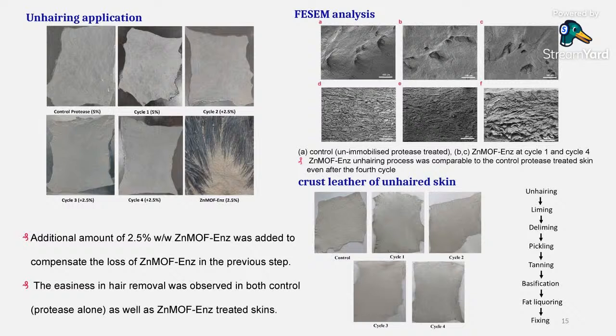Then we checked whether, after adding the ZnMOF in each cycle, the ZnMOF is doing any damage to the follicles, and whether the surface is smooth or not. For that, we did scanning electron microscopy. We want to confirm that the integrity of the skin is maintained. A is the control, and B and C are cycle 1 and cycle 4. Whether it is the control protease or the ZnMOF plus immobilized enzyme on the skin, everything is maintained very well.